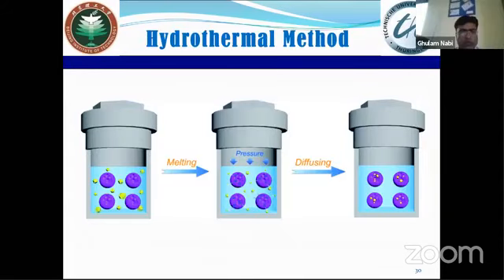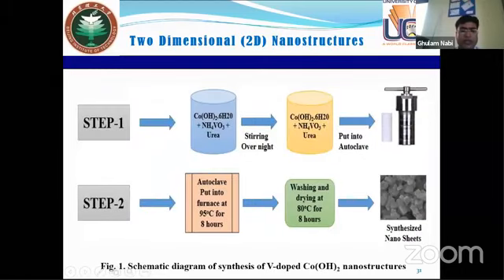The other method is the hydrothermal method, which is also a very common method. We can just take a solution of some precursors, put it into the autoclave and heat it up, and we can get the desired results. If we take a specific example, we have synthesized cobalt hydroxide and vanadium doped cobalt hydroxide for the application of the supercapacitor. Here is the block diagram for the synthesis of the nanosheets,